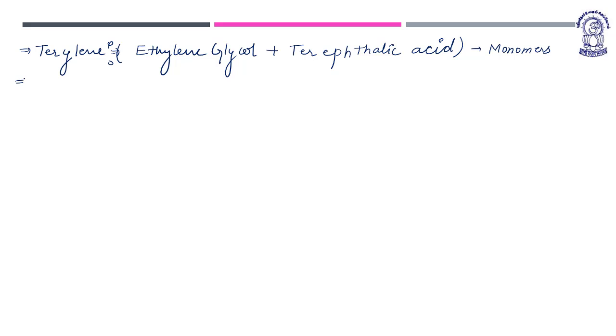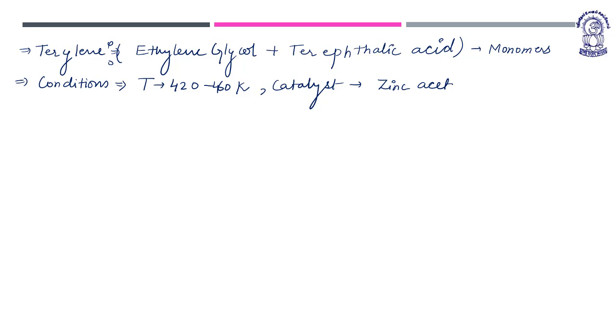The reaction conditions: carried out at a temperature of 420 to 460 Kelvin. Catalyst: zinc acetate and antimony trioxide.